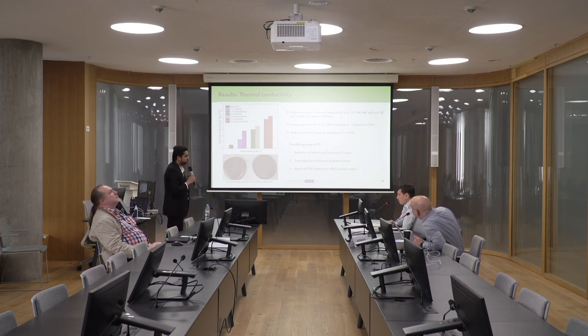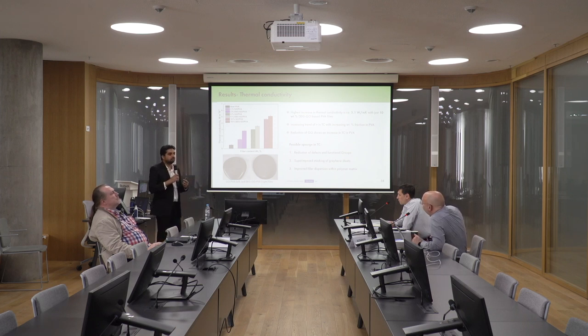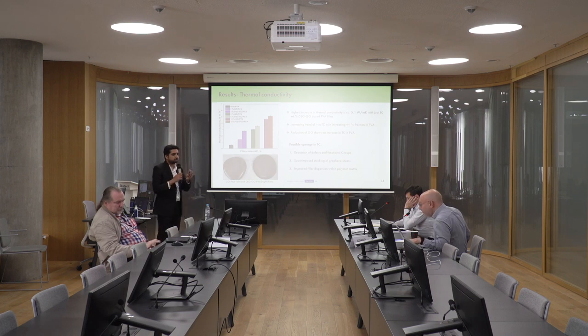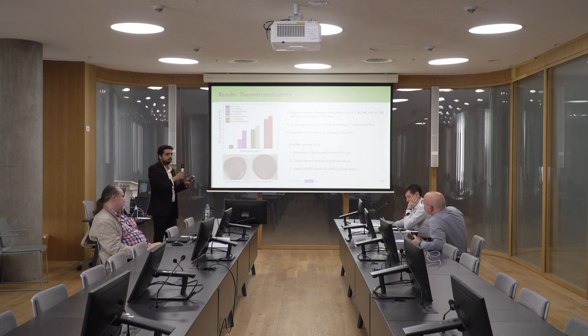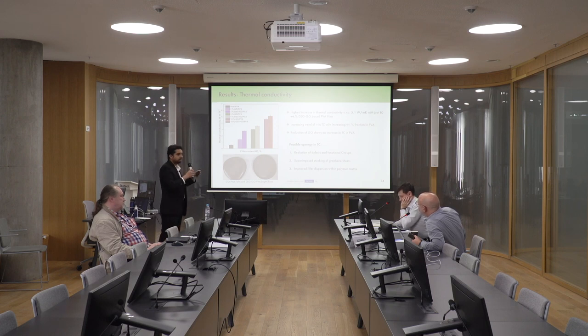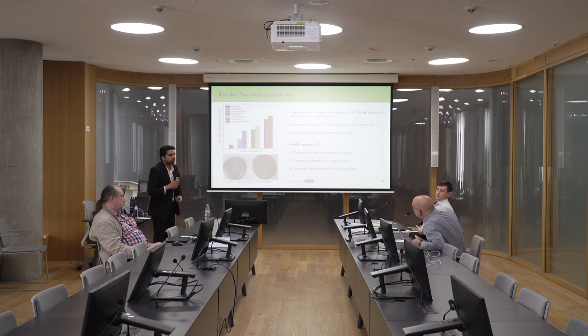Yeah, normally if you deal with the mechanism of thermal conductivity, if you increase the concentration of the thermally conductive particles, like graphene, which is highly thermally conductive at more than 5000 watts per meter Kelvin, the mechanism involved with the loading concentration is different. Even if you're talking about less than 1.8%, it involves the tunneling effect of electrons. But at higher weight percentage, there is a construction of thermally conductive pathways. But hang on, Mohammad.